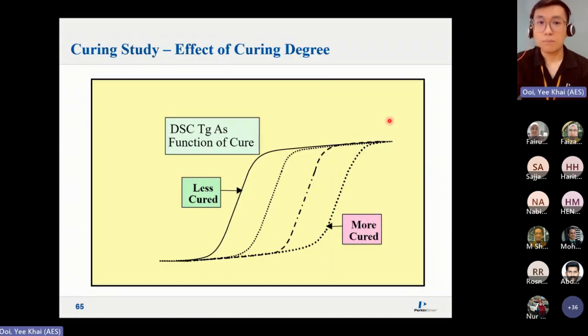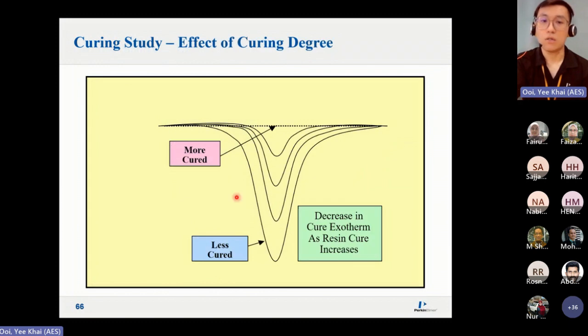So people use the Tg as the curing degree as well. The higher the Tg, the higher the curing or cross-linking percentage of the material. As you can see, at higher temperature it's more cured, at lower temperature it's less cured. Or you can use the curing peak as well. The curing peak is always exothermic. Just now you can see that a fully uncured material is going to have a very big uncured peak. The higher the curing percentage, the more the peak reduces, until you get a flat line indicating that the material has fully cured. So you can use DSC as a check for the curing degree of the materials as well. Okay.